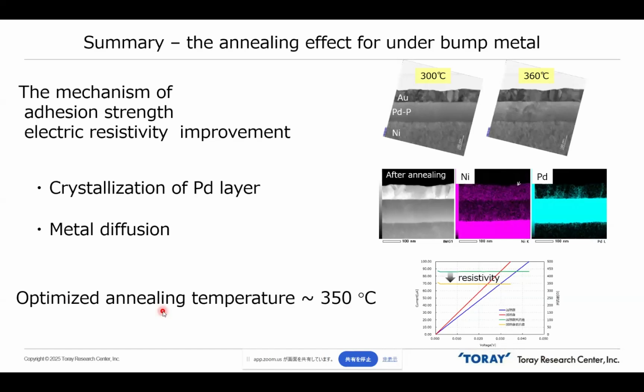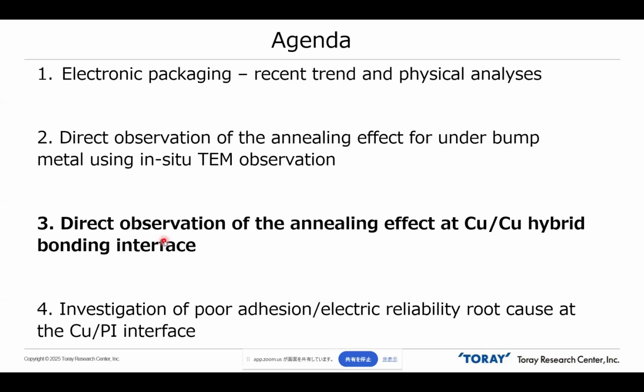Okay, I'd like to summarize this topic. We could experimentally detect the crystallization of the palladium layer, metal diffusion, and electric resistivity improvement in this sample in TEM. So we can say that the adhesion strength and electric resistivity can be improved by the crystallization of the palladium layer and metal diffusion. And we can also say that in this case, the optimized annealing temperature is around 350 degrees. Okay, then let's go to the next topic.